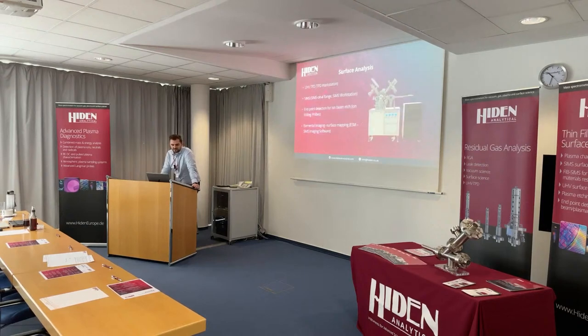For surface analysis, we have the TPD workstation, temperature programmed desorption, where we're looking at samples such as dissolved hydrogen in steels or deuterium in steels. So we heat up a sample and then measure the species coming off with our quadrupole mass spectrometers. We have SIMS, secondary ion mass spectrometry systems with integral ion beams to locally analyze surfaces. We work with ion beam etching systems, so we have ion milling probes as well. And we have custom software for elemental imaging and surface mapping.